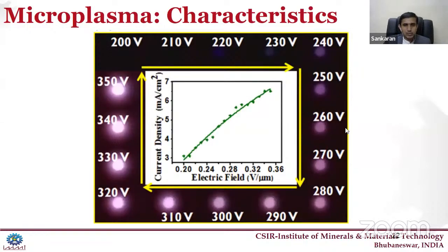These are the values we received first. With the increase in the applied voltage, the breakdown voltage is 220 volt. You can see the ignition of the plasma starts at 220 volt, so we call that the breakdown voltage. With the current density and the applied field, we can call it 0.22 as the breakdown voltage. Then increasing the voltage increases the plasma intensity, and we went up to 350 volt. We can even go higher, depending on your cathode material, but a lower voltage is better, where we get good plasma emission. So the breakdown voltage of our material is around 0.22.